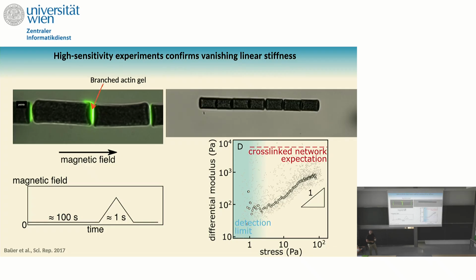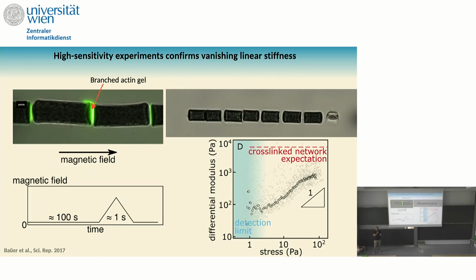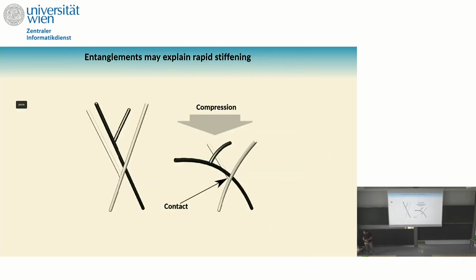That would correspond to the fact that, as I told you before, the branched actin is right at the edge of being solid or not. Okay, where is the elasticity or the nonlinear behavior coming from? And the answer is the following. The nonlinear behavior is coming from the fact that when you compress your branched actin, you are creating more and more contacts. Okay, you can make this assumption, but then it's very hard to explore experimentally.